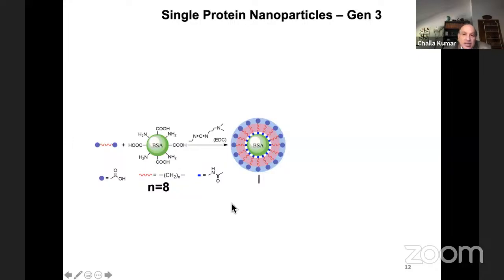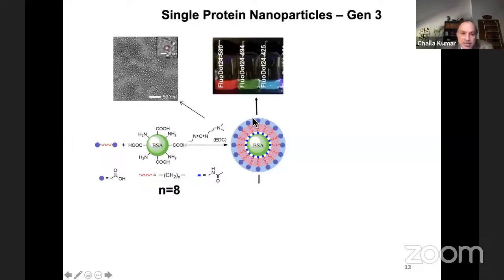artificial micelle, or single protein. We call it a single protein nanoparticle because this has a very finite shape, and you can see here, this is a transmission electron micrograph showing that the diameter of the particle is 10 nanometers. And this works out very nicely if you add the diameter of the protein with twice the length of the diacid, exactly 10 nanometers or so, approximately 9.5 to 10.5 in that range, based on how you use the conformations.